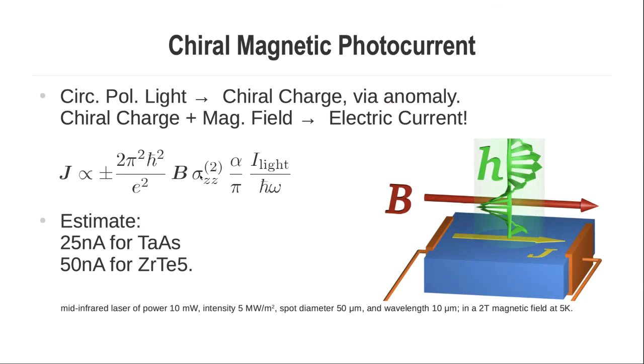The other remark I had is concerning the absence of the gap. In these materials, if you have a really Weyl or Dirac material and the Fermi level is close to the Dirac point, the conductivity is poor, and so, like in graphene, it's well known that there is a large variation of the chemical potential. Of course, your whole consideration is based on assuming that you have either electrons or holes. So inhomogeneity of chemical potential, which is present, for example, in graphene on the substrate, will violate the entire consideration if your filling is lower than some certain filling, such that all your sample is filled with electrons, no holes.